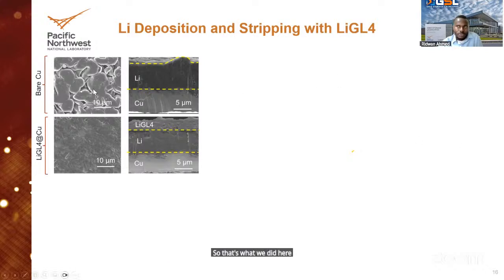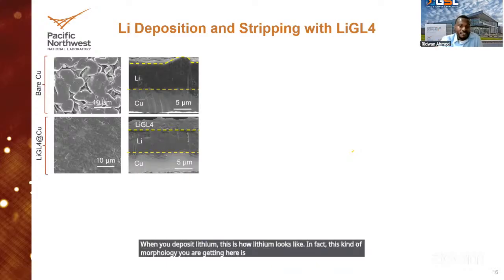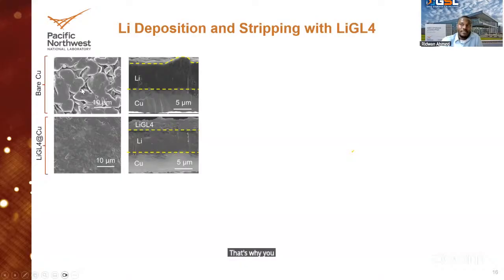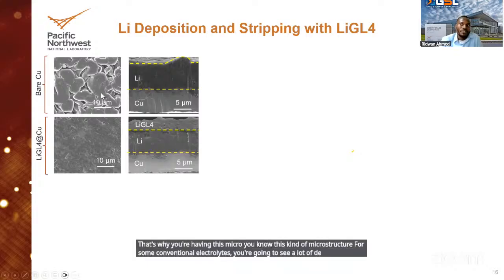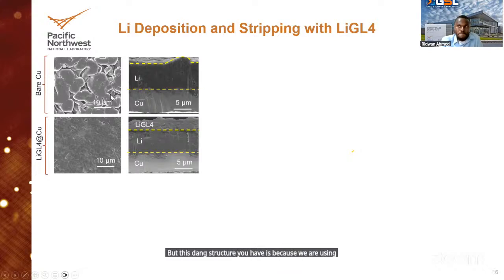So this is bare copper. When you deposit lithium, this is how lithium looks. In fact, this kind of morphology you are getting here is because the electrolyte we have is one of the electrolytes developed in our lab, which is one of the best in the world. That's why you are having this kind of microstructure. For some conventional electrolytes, you're going to see a lot of dendrites forming here. This is the cross section, which shows the copper and the deposited lithium.